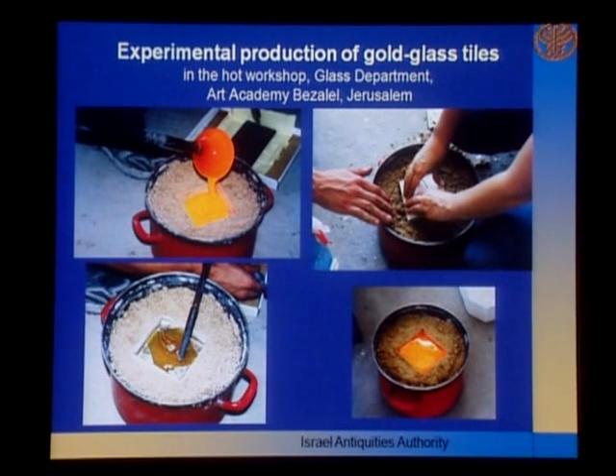In the spring of 2002, we were fortunate to experiment and explore the production process in the hot workshop of the Bezalel Art Academy in Jerusalem. During these experiments, we produced a few gold glass tiles, combining sand casting and blowing to examine the process and the results. First, molten glass was poured into a simple square mold in the sand. On the top right, you can see the preparation of the square mold, 10 by 10 centimeters, in the sand. On the left, you see the pouring of the hot glass into the mold. Then the student applied the gold foil on top of the tiles, bottom left.